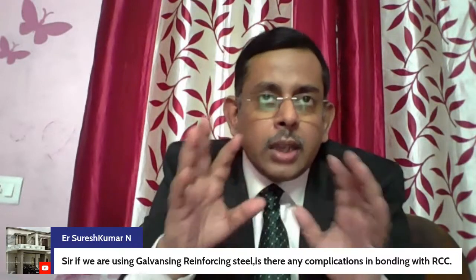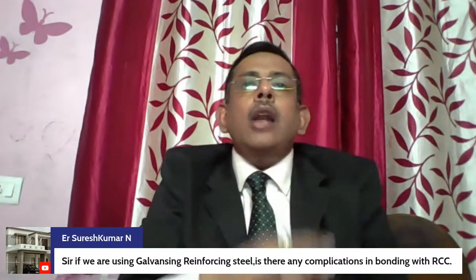I hope you are understanding my point. If you don't cover the place with galvanizing or zinc, you will have a bare steel surface, and your neighbors, that means adjacent areas, are galvanized. So you will have bimetallic conditions there, which will enhance the corrosion process. Welding will be the place where you will find corrosion if you don't coat the place properly with zinc afterwards. So the first step is that you need to remove the zinc before you do the welding.